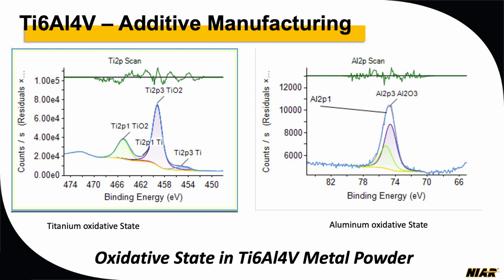As James must have pointed out earlier, if you compare SEM EDS and XPS, XPS is going to give you just the first 10 nanometers. So if the powder is, let's say, 3 micrometers, you're just going to get the surface of the powder. That's why you're going to see a lot of oxidation on your powders. That's what we are analyzing, looking at the powder at an initial stage and a later stage.